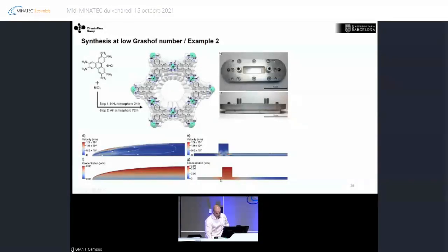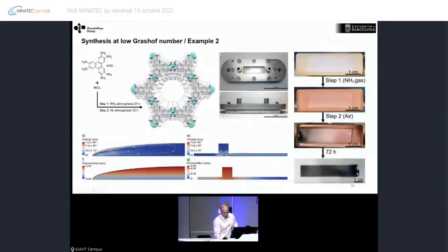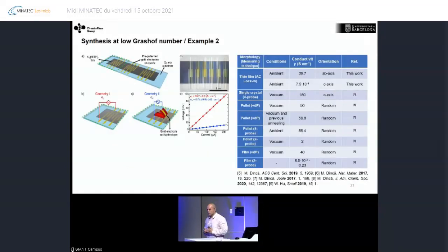So the Grashof number that we have here is very similar to what you would expect in the International Space Station. And what you see here is that while here the diffusion front goes in favor of gravity, in our case, it goes perpendicular. So it's like we are simulating microgravity conditions there. So doing that, what we observe is that now we can grow a really large film with this 2D conductive MOF. So this is also very important to mention. Because this is so large, we can measure this crystal in all directions.